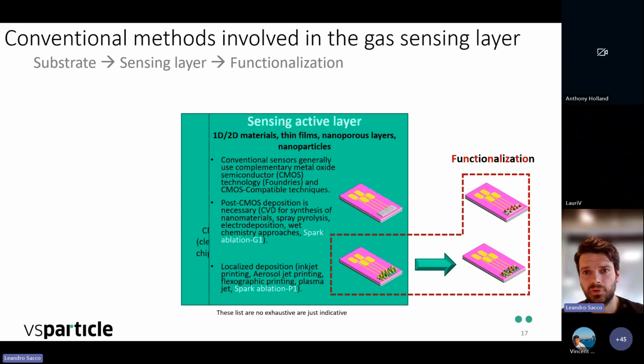And on top of that, of course, this is not the only way to do it, but typically we then deposit the sensing active layer. It could be done by CMOS compatible techniques, but for most of the nanomaterials, they need some post-CMOS deposition, like CVD for the synthesis of nanotubes or graphene. It could be spray pyrolysis, electrodeposition. There are a lot of wet chemistry approaches that you can use for deposition, and even spark ablation with the nanoparticle generator. But it's important to point out here that all these methods are not localized.